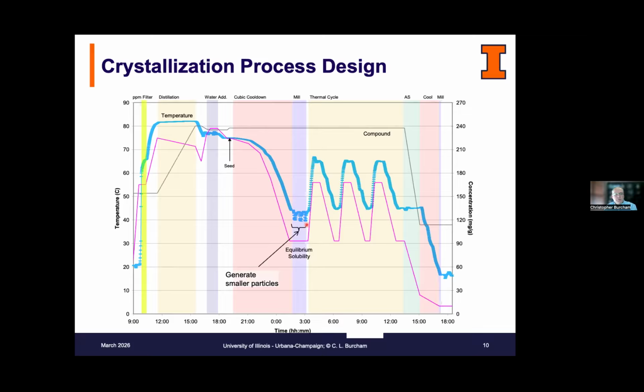At that point, we milled the material, and this was the change. We milled the product, and then we thermal cycled it. Why did we thermal cycle it? We did that so that we could dissolve the fines that were produced, as well as play on the difference between the growth rate and dissolution rate of the different phases. And in doing so, by the end of the third thermal cycle, we ended up with material that had a much improved crystal habit. All of this was done above that enantiotropic crossing temperature of 45°C. And by doing that, we were still in a thermodynamically stable region for that crystal.